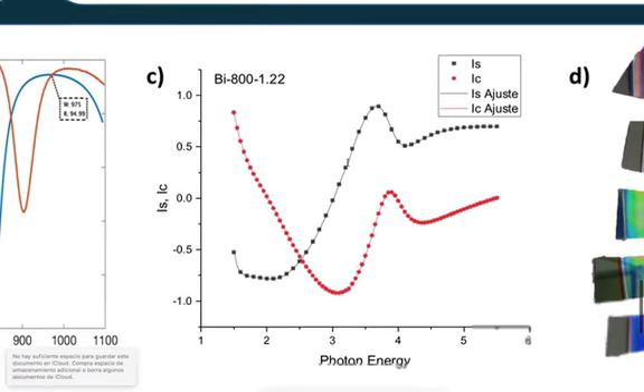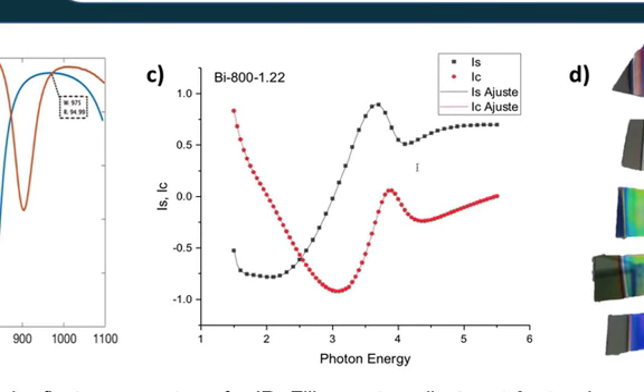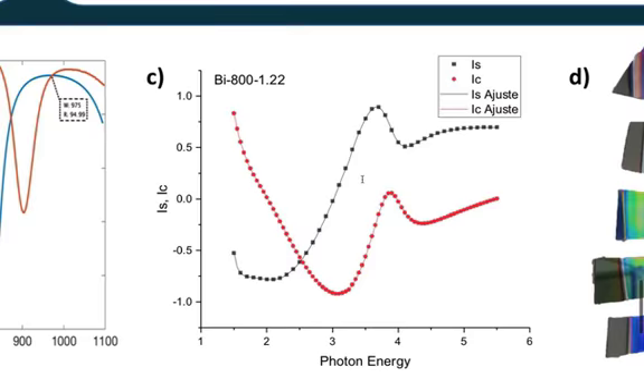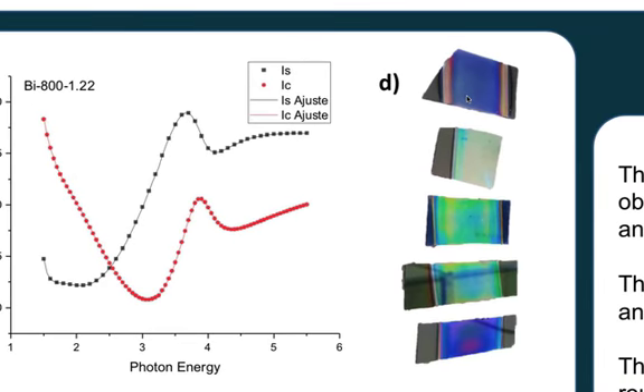The adjustment was made by ellipsometry to samples smaller than 100 nanometers for both materials and with a double layer, with the values for the visible range, which is why the result is a better fit in the region that is visible. Here we can see some samples. The color is characteristic of the region to be reflected.